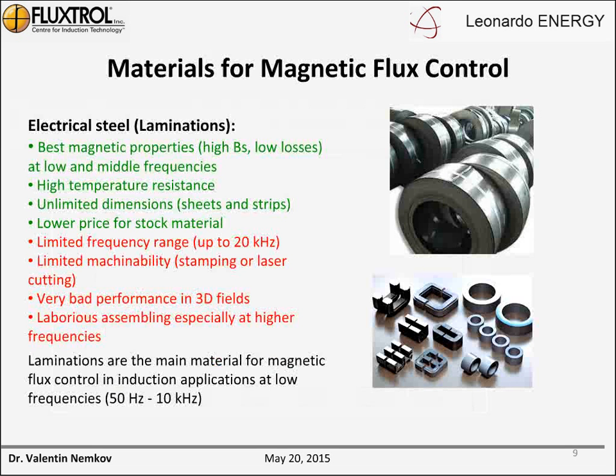So let's consider what are the drawbacks and the advantages of different materials for magnetic flux control, specifically in induction heating. Electrical steels have the best magnetic properties, low loss and high saturation flux density at low and middle frequencies. They have high temperature resistance. In general, laminations are very mature materials, and we have wonderful electrical insulation, aluminum phosphate, that can tolerate temperature up to 500 C and so on. It's a great material.